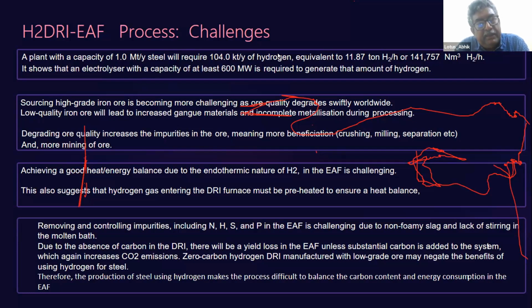But the other thing is that it's endothermic, so it cools down, and so it needs preheat. It needs energy supply from the outside. And also some characteristics of the slag impurities that dissolve, they are not foamy, so it is very difficult to separate out the slags from them. It's a challenge. And in order to do it, you have to add carbon. And again, then what happens? You are adding carbon, you are adding heat, adding energy, just to reduce the carbon dioxide. But again, it negates the benefit. Okay, so these are the challenges. These are the challenges for the future.